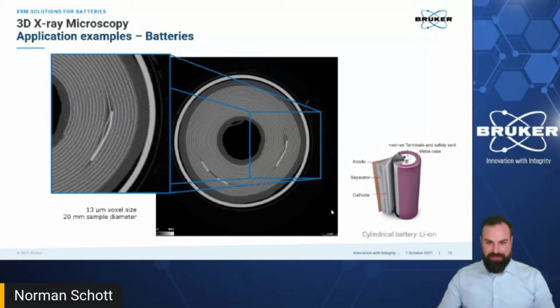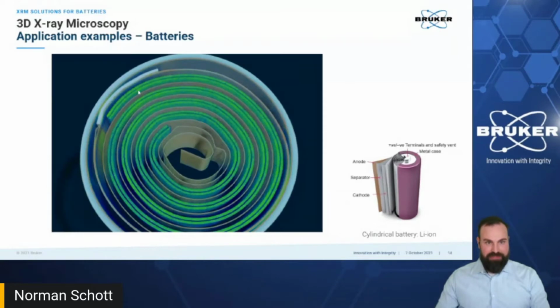The next example is a normal round cell. Here we can see the single layers. We can see the cathode, the anode, and in between the separator. We can analyze that everything goes well in the manufacturing process. We can also analyze the thickness of each layer. Here, green means everything is in tolerance. When there is a part that is too thin or too thick, the color will change to blue for too thin or red for too thick. So this is a really quick method to check if the layer is okay, and also a method to check in the whole battery if the layers are okay.